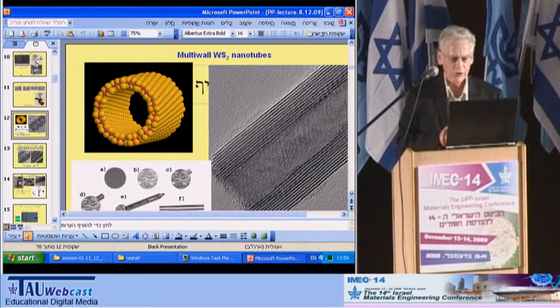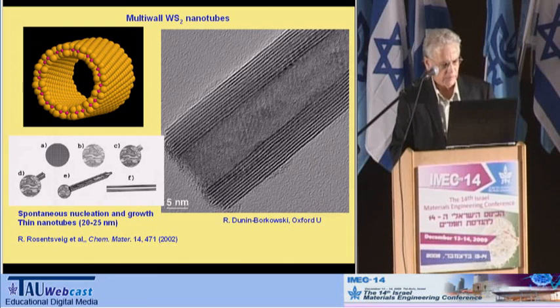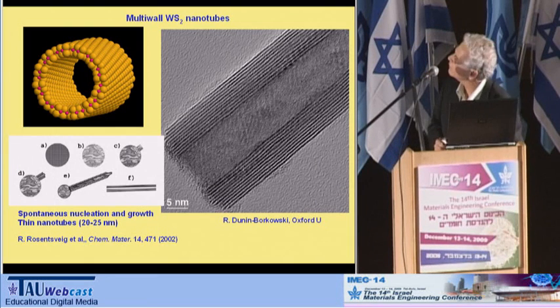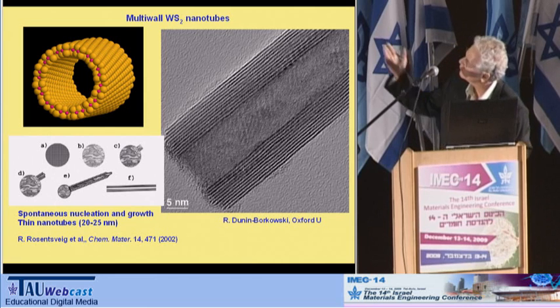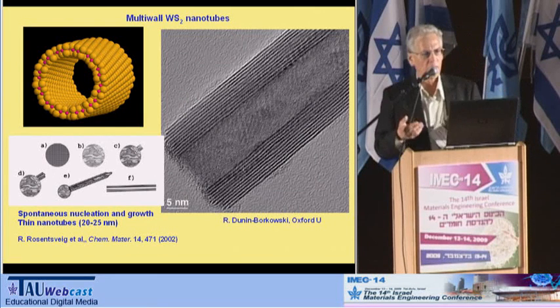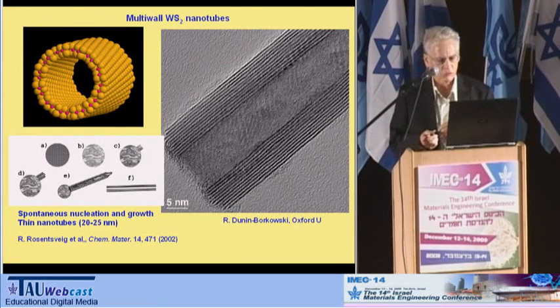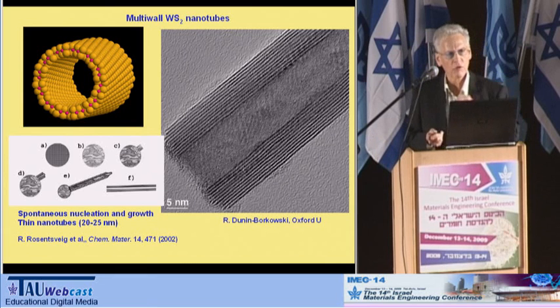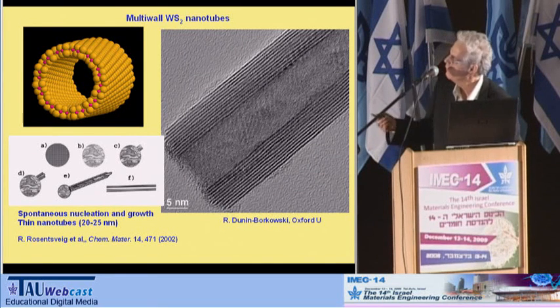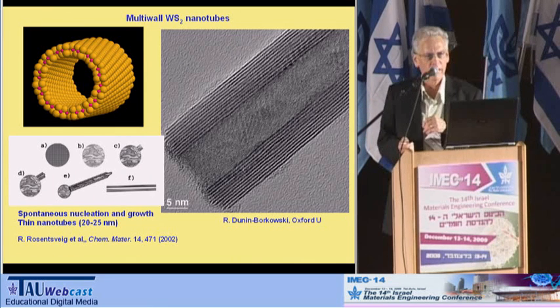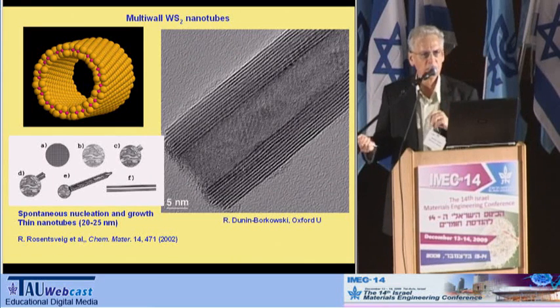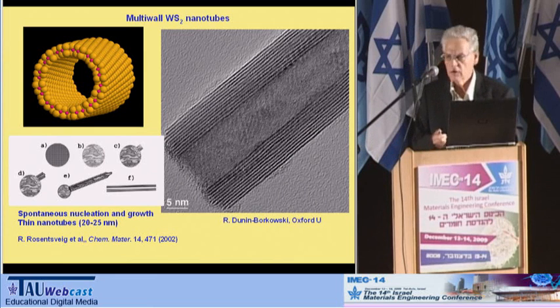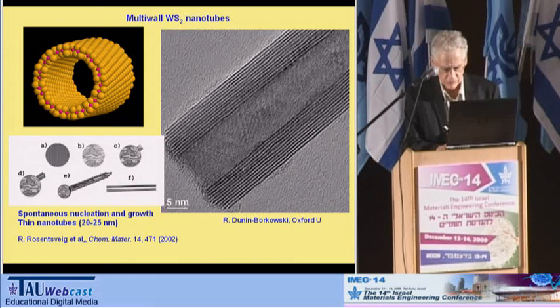Let me go now into the nanotubes. And the nanotubes have been observed at the same time that the nanoparticles have been observed. And now you see the perfect nanotube. We now know for the tungsten disulphide there are two growth mechanisms. One growth mechanism gives rise to very narrow, slender nanotubes with about 5 to 10 layers, 20 nanometers in diameter and about a few microns in length, very perfect in shape.